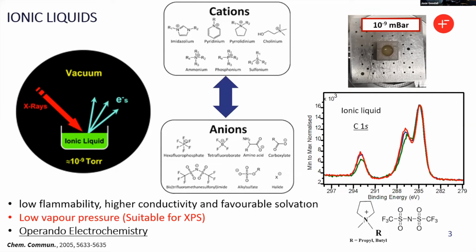It was there for at least 1 week, and it was stable, and the spectra were almost identical. So they were very stable. The only change in spectra could be due to the degassing of the sample. Liquids tend to absorb gases and water pretty easily, and it slowly tends to degas, and that might lead to a change in the spectral features.